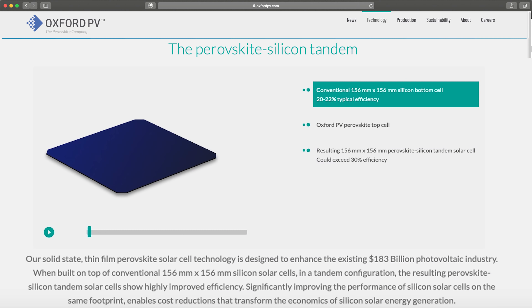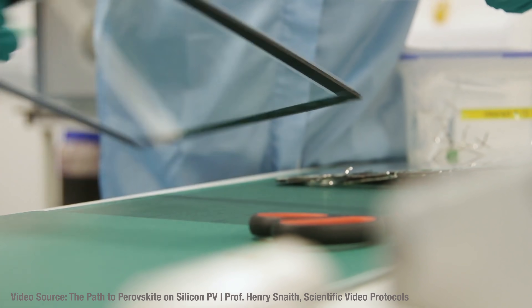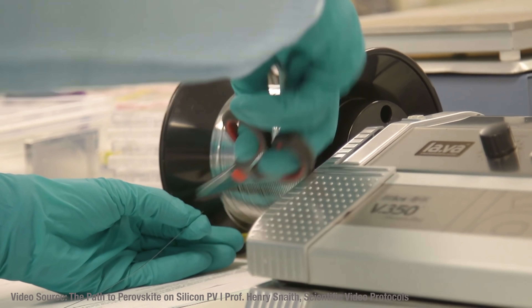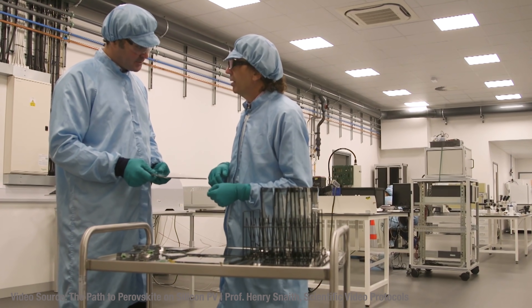The simplest way is to put a perovskite cell on top of silicon. Silicon-perovskite tandems have already reached 29.1% efficiency — much higher than the 23% for a single junction perovskite cell, and higher even than the all-time world record for crystalline silicon using very advanced technology, which is 26.7%. Professor Snaith is confident that with a triple junction cell, they can push towards 40% efficiency — that could be two perovskites on a silicon cell, or an all-perovskite combination.